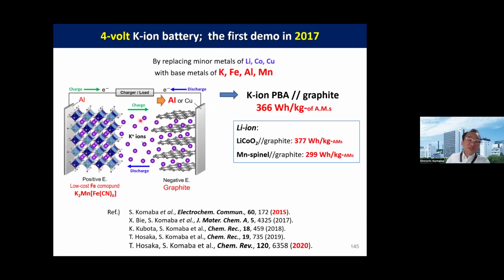So in our recent study, one of the best combinations as positive and negative electrodes is manganese hexacyanoferrate and graphite electrode, respectively. Based on the half cell test, we can reasonably expect a higher energy density. And this energy density is comparable to some of the lithium ion systems.